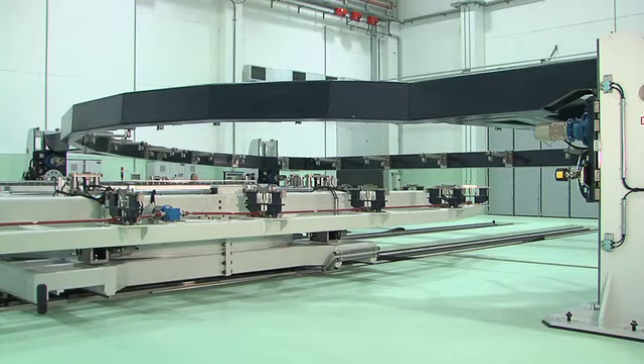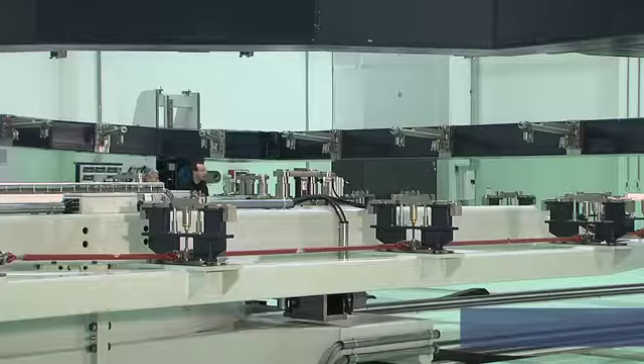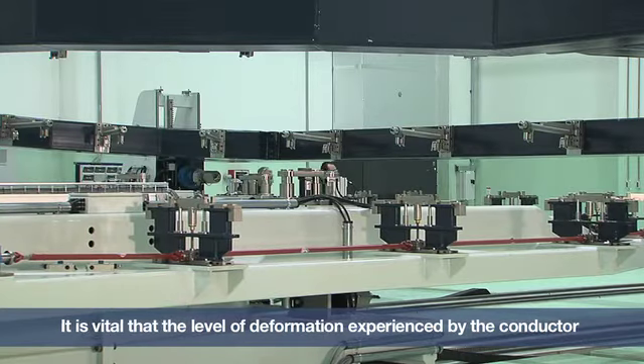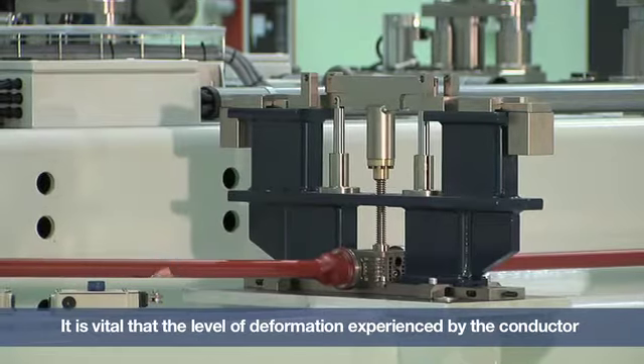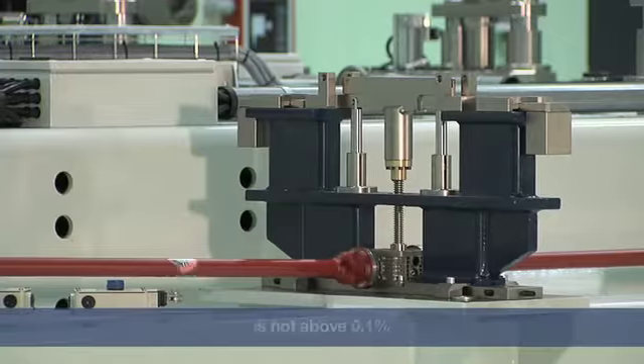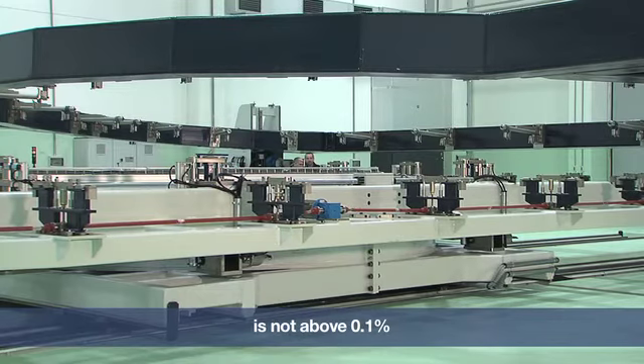The function of the insertion tool is to insert the double pancake conductor inside the groove of the radial plate. This is a very critical operation because during the transfer, the deformation experienced by the conductor cannot exceed the value of 0.1%. Otherwise, the superconducting wire will get damaged, reducing the performance of the superconductor and, as a consequence, the performance of the TF coils.